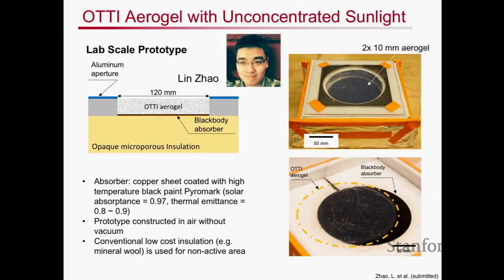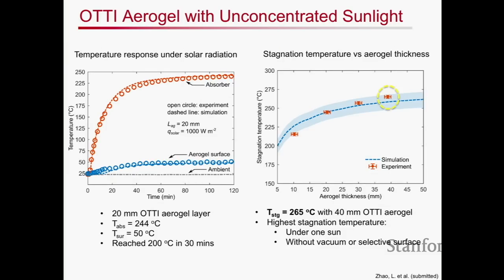Right. So the experiment that we set up is just using black paint, a Pyromark paint. The solar absorbance is on the order of about 0.97 and thermal emittance is about 0.8 to 0.9 or so. And again, we're constructing this without any vacuum, so it's just in air. What we've done to insulate the rest of it is just a conventional low-cost insulation for the non-active area. And these are results from the experiments which show a lot of promise.